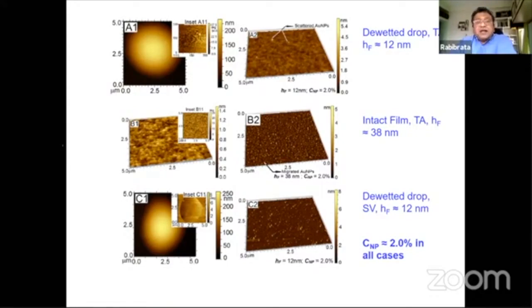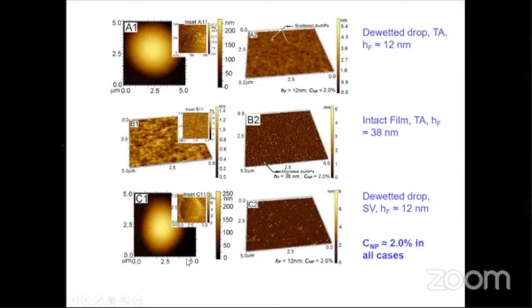So what we did was some very careful atomic force microscopy, and we saw that the particles, actually, you can see in the atomic force microscope image that the particles agglomerate on the top of the surface of a dewetted drop when you do a thermal annealing, as crowns. In contrast, since the solvent has gone all the way down to the substrate, a dewetted drop through solvent vapor annealing is completely pristine on the top.